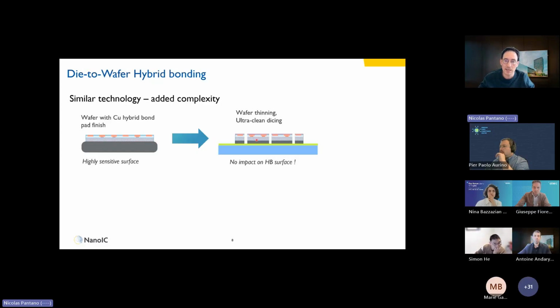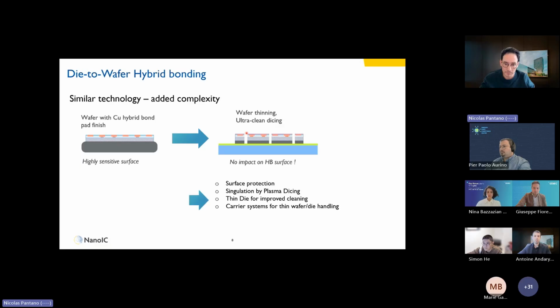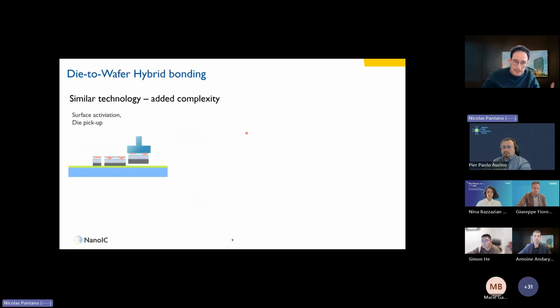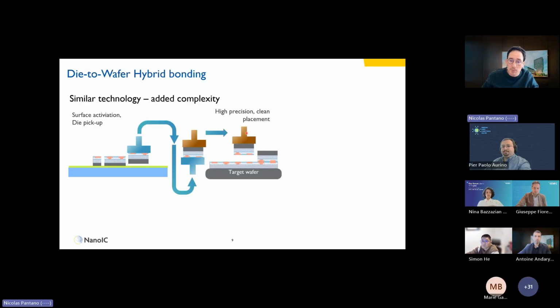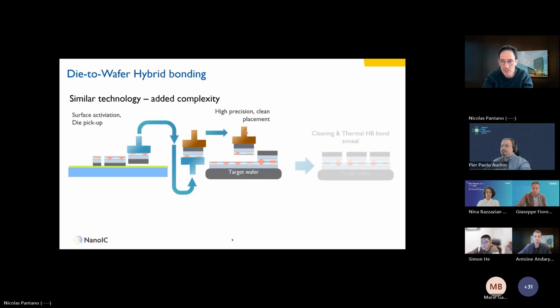You also need to singulate this die, and by singulating, they need to be clean and pristine, especially at the hybrid bonding surface. So that's also a very complex dicing process, which doesn't use blades, but a litho process. Then you take a die, you flip it, and you place it on the target wafer. Obviously, if you want to have 2 micron pitch, you need a precise alignment, which is not helping in the complexity. But ultimately, you will end up with a clean system, hybrid bonding, no gap between the 2 chips. And if you even do a cross-section, it's difficult to identify where that interface is located. So it creates like a monolithic block of 2 silicon chips.